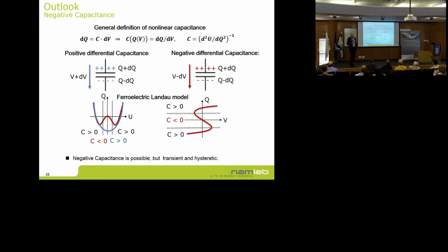Now let's go back to a ferroelectric. Landau theory predicts this curve of the energy landscape, energy via polarization or charge. If I look at a normal capacitor, and this is the voltage and this is the charge, then I would have one stable point at 0 volts and nothing else would happen. In the ferroelectric, I have these two minima, these two stable states, but in between I have a region that's locally going the other way around. So in principle, there I have my negative capacitance region, but of course, it's not stable.